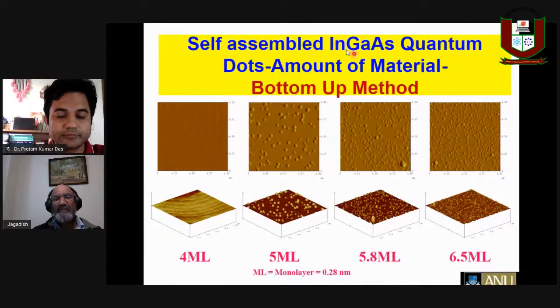And we try to grow indium gallium arsenide on gallium arsenide substrates. Because of the large lattice mismatch, you introduce a lot of strain. Initially, if you deposit about 4 monolayers, a monolayer is about 0.28 nanometers, I'm talking about 1 nanometer or so approximately here.